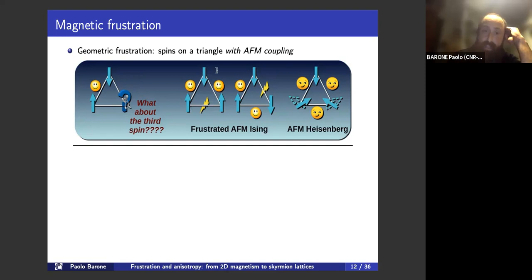This is particularly evident in the case of Ising spins, because they can just point up or down. So we cannot find a situation where all the bonds are happy, without an energy cost due to the antiferromagnetic interaction. In the case of Heisenberg spins, instead, spins can rotate in order to minimize the energy due to the antiferromagnetic interaction. And typically you find this 120-degree configuration. We have two isoenergetic configurations, which differ only in the handedness of the rotation. So they basically have opposite chirality, but are still degenerate in terms of energy.